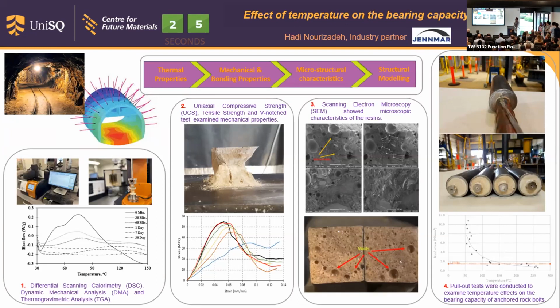In this research, we conducted a comprehensive experimental study to evaluate the behavior of this system at higher temperature. By conducting several pull-out tests, it was concluded that the axial behavior of these elements decreases significantly when the temperature of the environment reaches around 50 to 65 degrees.